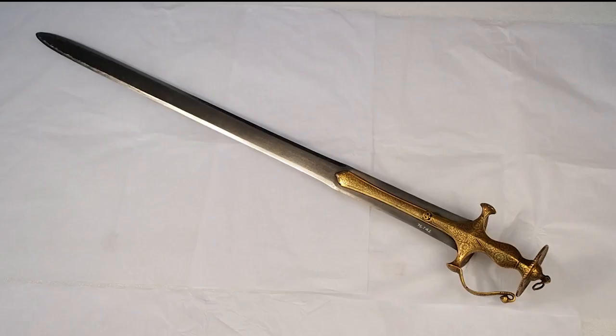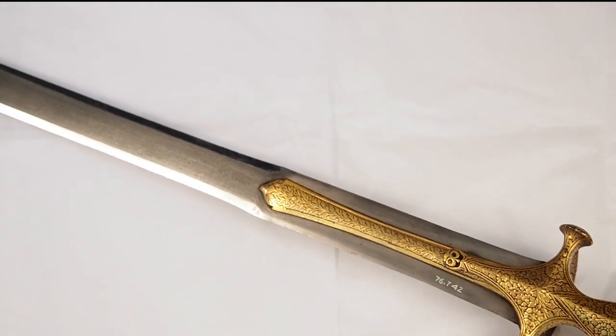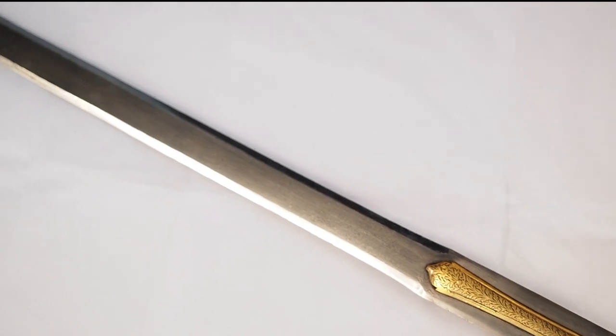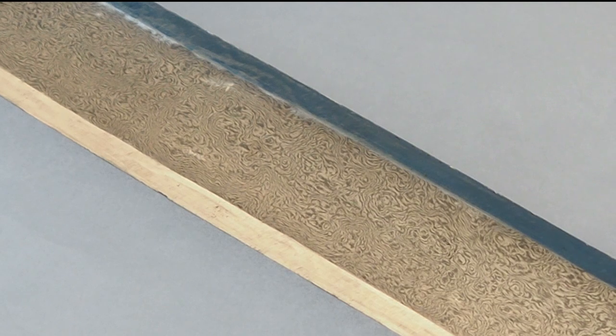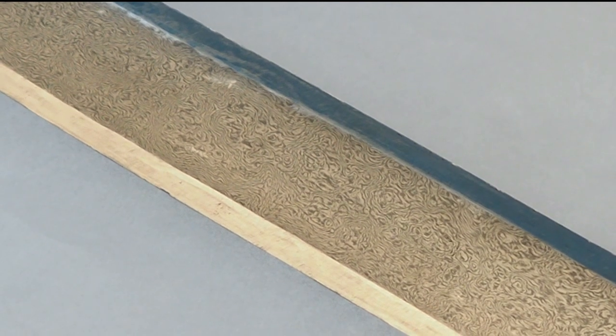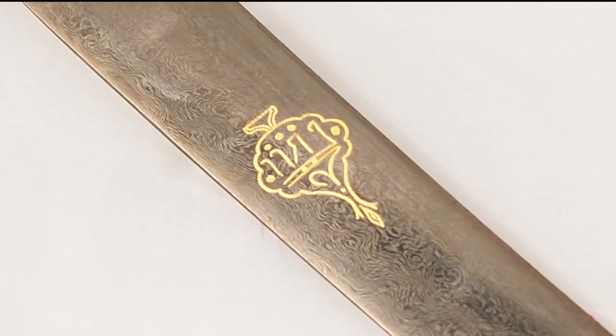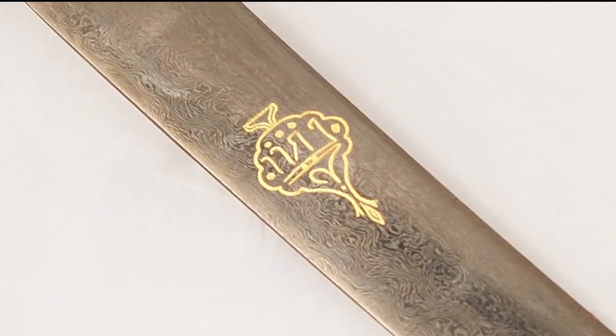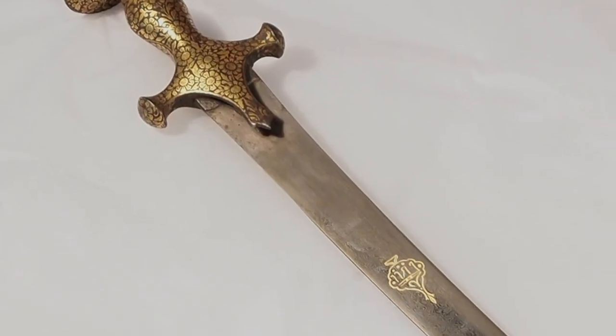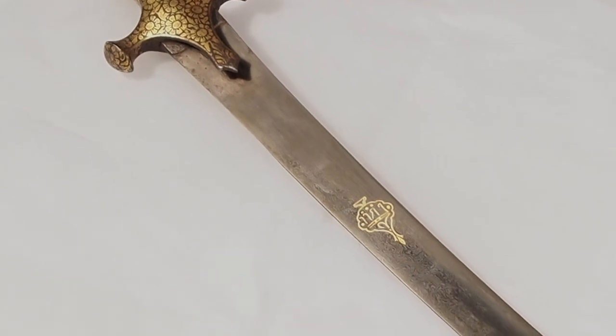The fabled Damascus pattern was generated by forging the wootz ingot followed by etching, contrasting the dark perlite layers with light cementite. The swords could be forged to a very high extent due to the property of superplasticity or high forgeability at high temperatures. Mr. Rakesh Sharma, curator of the National Museum, explains the structure and the quality of Damascus steel blades made of wootz steel. And you could see that the quality of this blade,